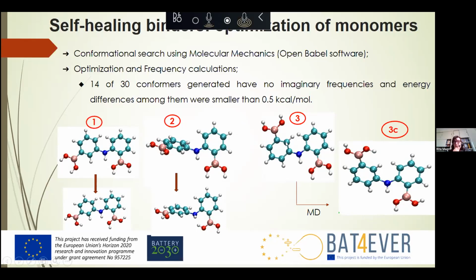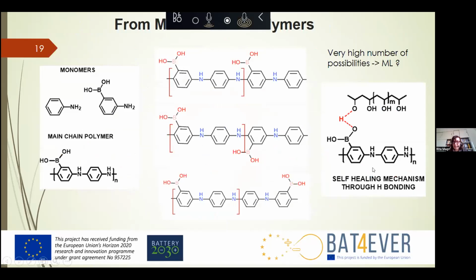When we use them in the molecular dynamics run, we found, very strangely, that the OH bonds are not staying like that, but they prefer this tilted geometry. We resubmitted this geometry to DFT and found that it actually is the lowest energy configuration. So the bonds are tilted.